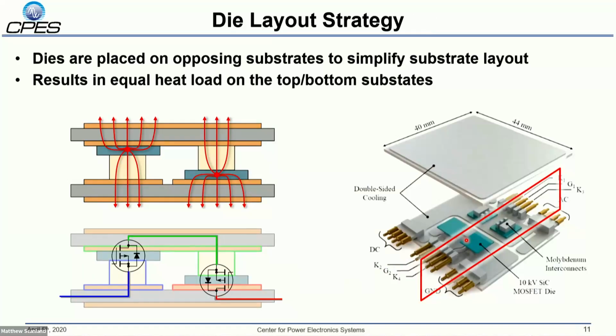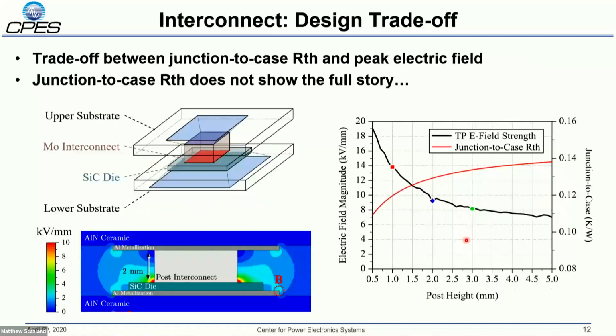You'll also notice that we actually have these die flipped around a little bit. So some of these die are mounted on the bottom substrate. Some of these die are mounted on the top substrate. And part of this is an electrical routing issue. Because this is a phase leg structure, alternating the die placement like this makes it a little bit easier to do the electrical routing. But it also allows us to share the heat flux between the top and the bottom side cooling surfaces. So if we have any mismatch in the heat flow from the top and bottom, flipping these things around gives us symmetric heat flow so we can get the best utilization out of our coolers.